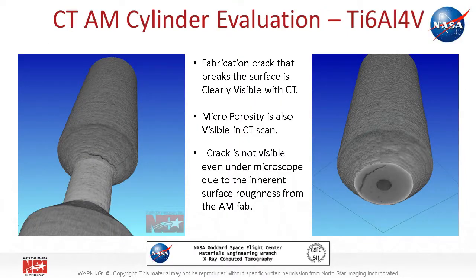The following few slides will provide examples of AM products being evaluated at NASA Goddard Space Flight Center using an NSI CT system. The first sample here is an AM cylinder that's being evaluated, and there's a fabrication crack that breaks the surface, and it's clearly visible with CT. However, it's not visible even under a microscope due to the inherent surface roughness from the AM fab. There's also microporosity that's visible in a specific slice area in close proximity to the crack.